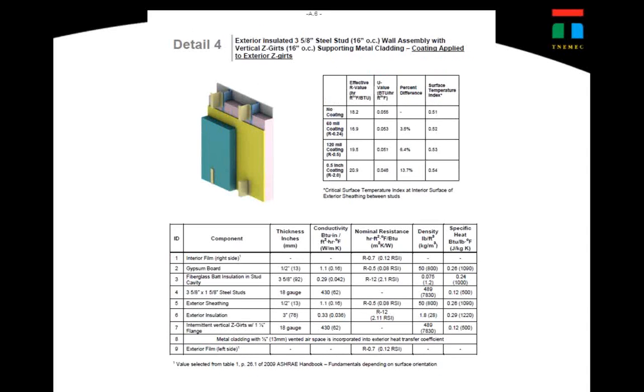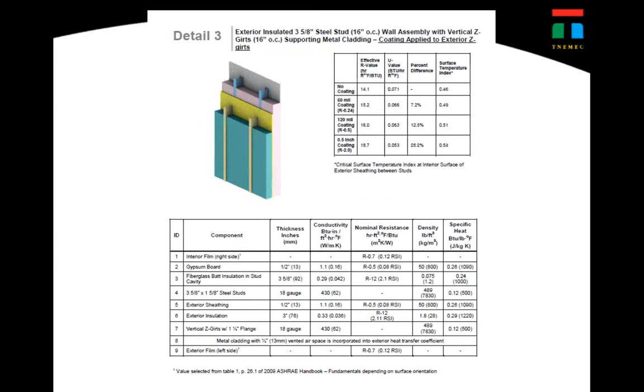Hi, Greg. It's Mark. If you could go back one slide to detail 3. So the Aerolon coating is actually on the Z-girts that penetrate through what appears to be blue insulation, and that creates your thermal break? Yes, that is what you see. Anything that has the beige color there, that is where the Aerolon has been applied in this particular application to metal studs, right? And actually, you can't see it here, that's just on the exterior fascia of the metal stud. It wasn't the entire metal stud. So just the outside strips, that 3 inches, is what you're actually coating there. So if you have a cladding system that was held off by Z-girts, once you put in the insulation, potentially you could just add the Aerolon coating and then screw your cladding to it and it would perform? Correct. Wow. Okay. Thank you.